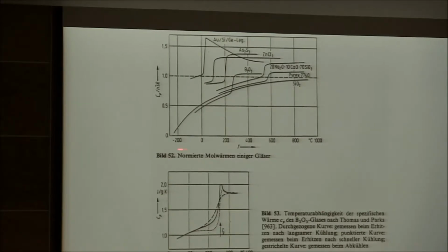This is a diagram from an old German textbook called Glass. And what they describe is this strange jump or bump in the value of the heat capacity. So the amount of energy I need to move this material up 1 degree for a certain mass unit, right? You would think that it's smoothly changing with temperature. In all crystalline substances, as long as they don't undergo a phase transition, they will give you a smooth temperature dependence from the bottom to the top. In this case, you don't get a smooth transition. What you get is a transition somehow, a jump.